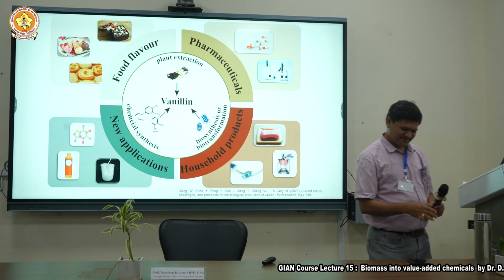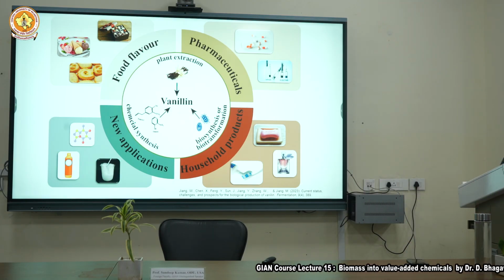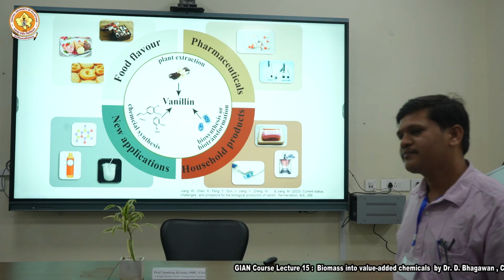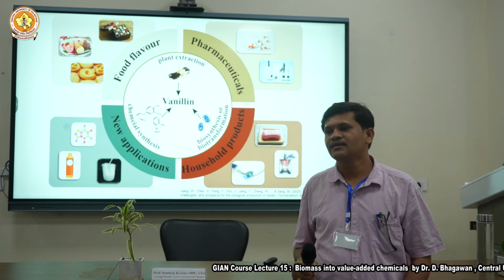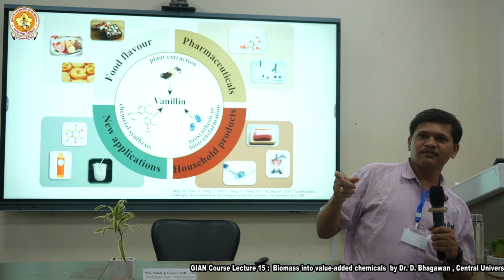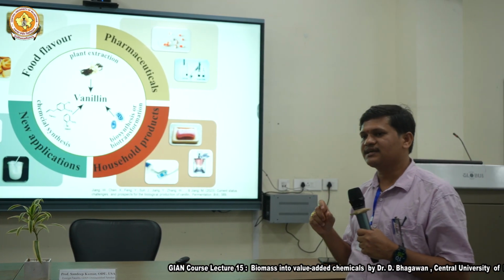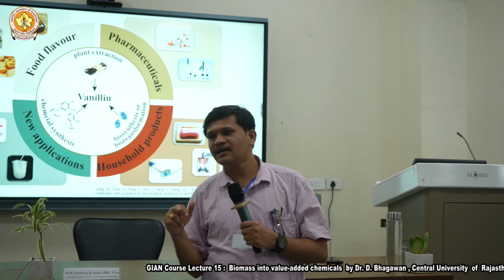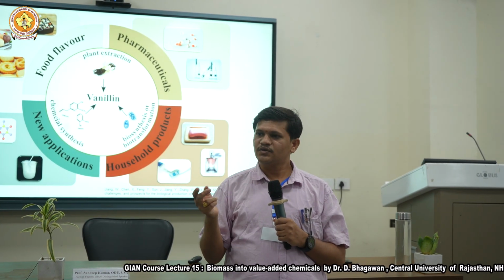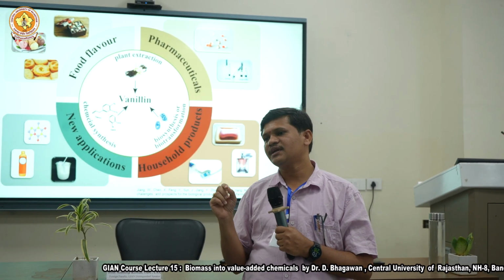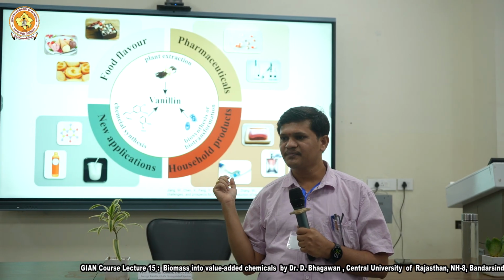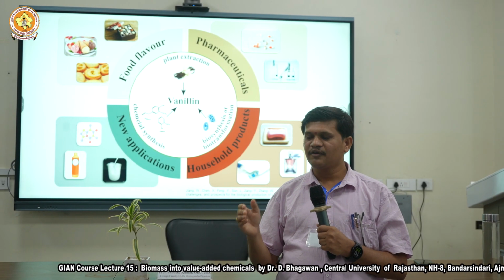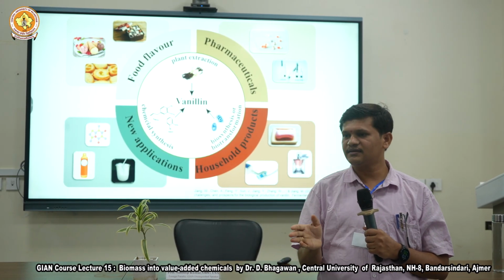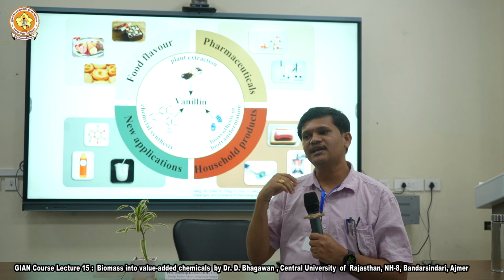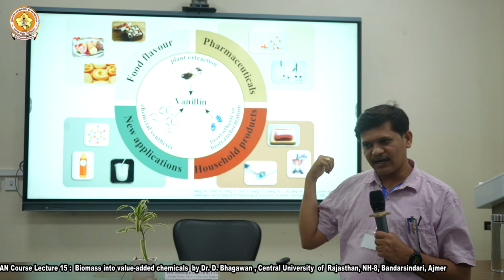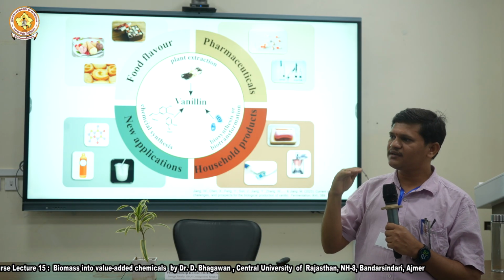Yes, please. Apart from the 30% loss which is occurring because of some chemical, is any kind of doping or modification possible for enhancing the yield? Obviously, it is possible when we go for designing of the catalyst. And the second thing is the light which we are using. At a selective wavelength, we have the capability to enhance the selective oxidation species. So if we use 365 nanometers with the selective range, with a filter, like exact filtration, then we will generate the selective oxidation species under the designed catalyst. That way we can enhance our yield.